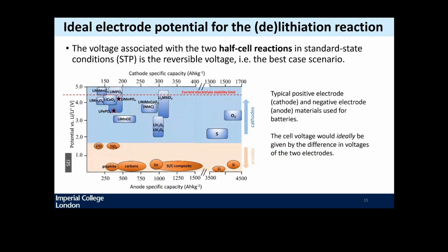And you can do this for a lot of different materials. And I put here some of them that are of interest for battery electrochemistry. So based just on the thermodynamic potential obtained via the Nernst equation and obviously validated by experiments, you see here we can build a chart. So on the y-axis you have the potential, this thermodynamic potential of the different materials, and in orange are materials that are usually used for negative electrodes, and in blue are materials that are used for positive electrodes.